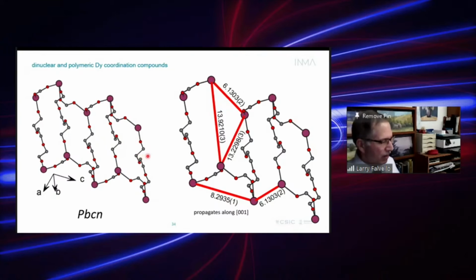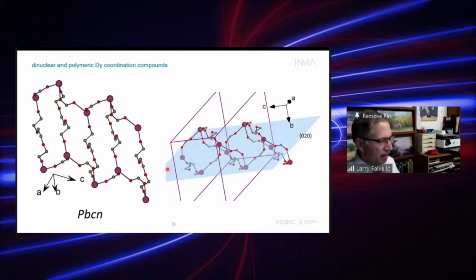And the question is, okay, what information would we get or lose if we measure a single crystal? Right? Now, there are a lot of different dysprosium distances here. I'll note the 13 angstrom one, because we'll see it again in the dinuclear compound. But if you take the best plane through this staircase, the best plane through a staircase is kind of a diagonal along its propagation direction. That plane is the 0, 2, 0 plane of the orthorhombic unit cell.